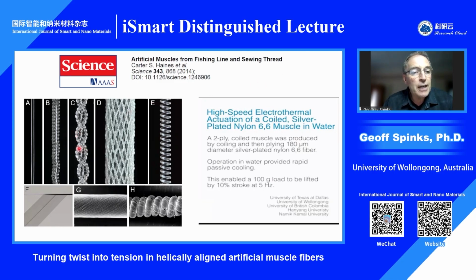It involved essentially taking textile fibres, like nylon fishing lines or polyester sewing threads, and really any kind of textile fibre, twisting them and then over twisting them so they produce these coiled shapes like is shown in figure B here on the left. And at that point, they can then be actuated by heating, and that causes a length contraction, which is reversed on cooling. Sometimes the fibre is coated in a conductor, such as carbon nanotubes, and that's to allow electrothermal or Joule heating, which is a more convenient way of heating. But the performance can be really outstanding, as illustrated in this video.